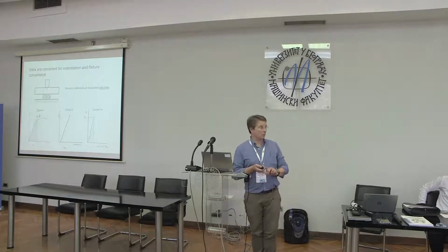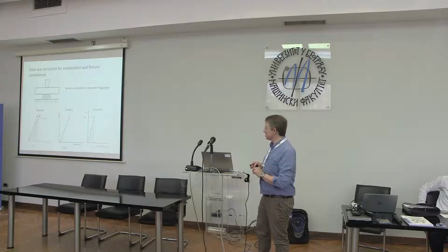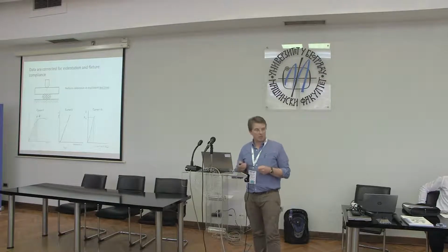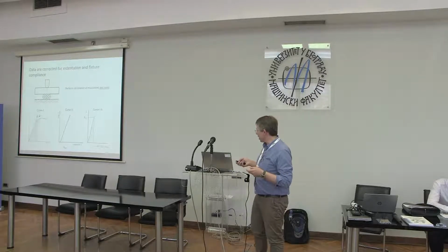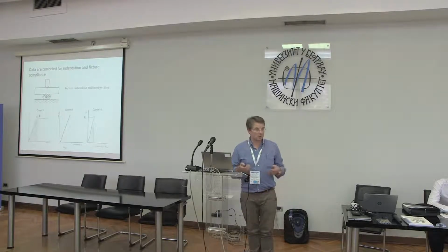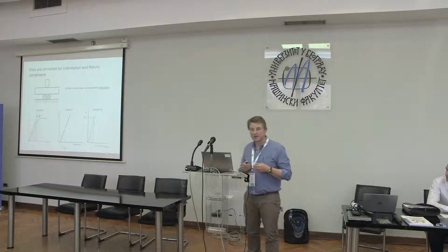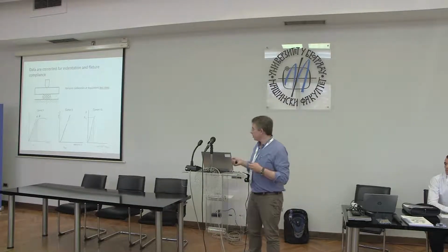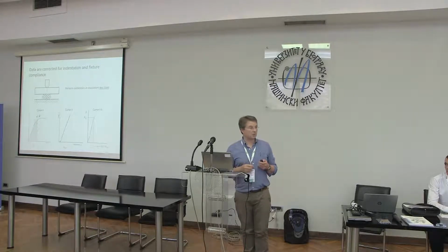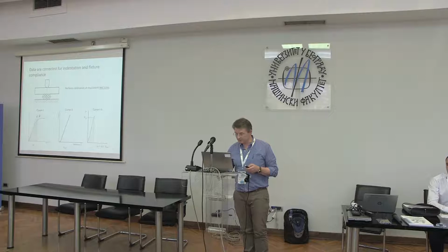So you have a way of correcting the data. An important thing to do, because polymers are viscoelastic, we do this at a fixed rate, such that the total test time is the same as you obtain in the fracture test. So the rate is equivalent, and we do these corrections at the correct rate. So we have curve 1, this one on the left, which is our test result. We have our correction curve from our indentation test there, and then we have a corrected curve where we subtract one from the other to give us our modified displacement versus force profile for the corrected experiment. You may be familiar with this.